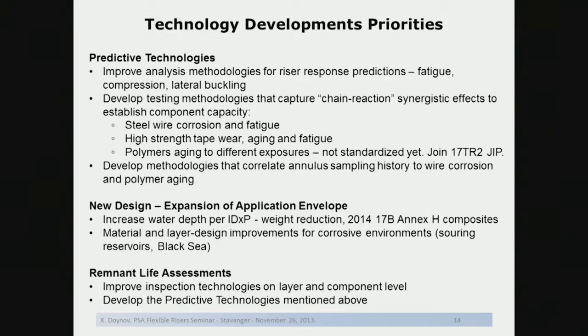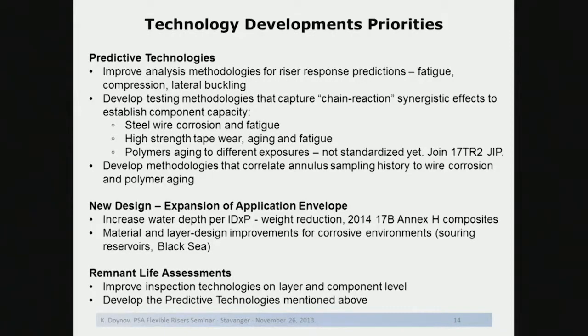On the new design, the importance is expansion of the application envelope, and specifically to increase the water depth for existing diameter times pressure, which essentially means weight reductions. What we have done in the upcoming version of 17B, we introduced Annex H that actually introduces a framework for the introduction of composite materials and components and layers into the unbonded flexible pipes. Then the other area is material and layer design improvements for corrosive environments, specifically for souring reservoirs, which is a fairly recent phenomenon from the 2000s. And for the strange environments like the Black Sea, where we have hydrogen sulfide and no oxygen whatsoever beneath a water depth of about 200 meters.